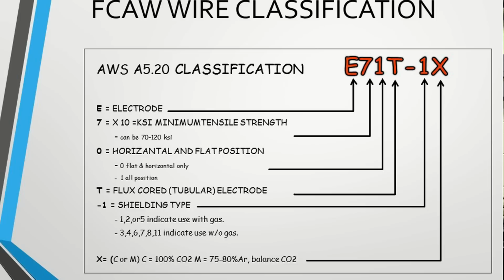Just because you're using an all-position wire doesn't necessarily mean that an all-position wire is best if you're only welding in the flat and horizontal positions. An all-position wire has a very fast freezing slag system, and so if you're welding over some mill scale or rust, then using an all-position wire may allow gas to get trapped, causing porosity in the weld bead. If you used a flat and horizontal wire, it would have a slower freezing slag system, and this would allow some of those gas pockets to escape rather than getting solidified underneath the slag system. So just keep that in mind when you're using your all-position wires in position.